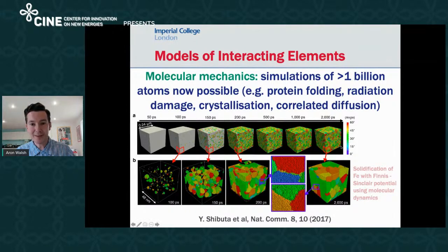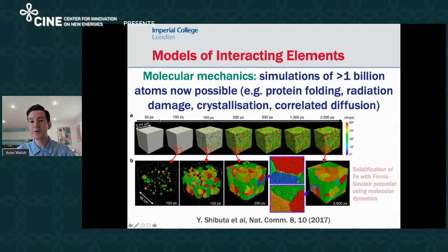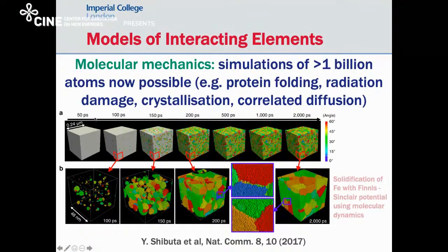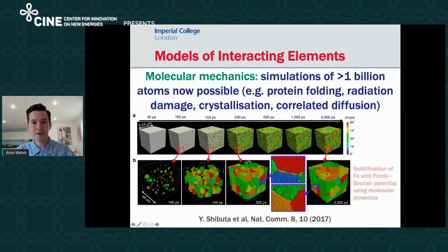And this is just one recent example from the literature which I really like. It's taking a large simulation cell of liquid iron, cooling it quite slowly, and what you see is the emergence of microstructure. This is using quite a simple interatomic potential. That microstructure wasn't included in the original model, but it emerges due to the collective interactions between the atoms in the system. So without worrying about it, you actually get the emergence of grains and grain boundaries and dislocations. It just shows you how quite simple models of interatomic interactions can give you quite complex materials behavior.